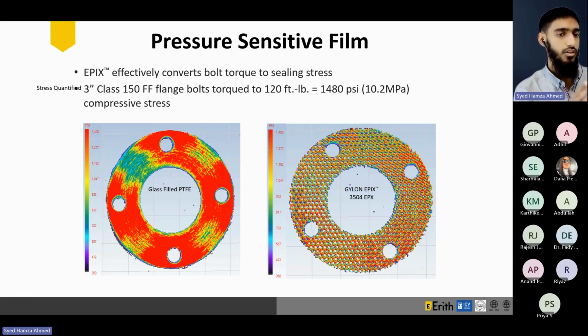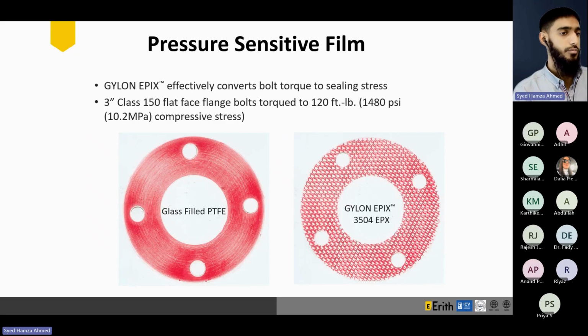As you can see, on the right hand side, you have the Gylon Epix model. Due to its pressure sensitive film and the hexagonal profile structure on the surface, we see an even distribution of the bolt loads in the gasket, which is transformed into uniform gasket stress all throughout the surface of the gasket. Again, this is without the pressure gradient. The same 3-inch pressure class 150 flat face flange. You can see the comparable values of stresses on the left side and the right side, as you have the Gylon Epix model, which has even distribution of the pressure.